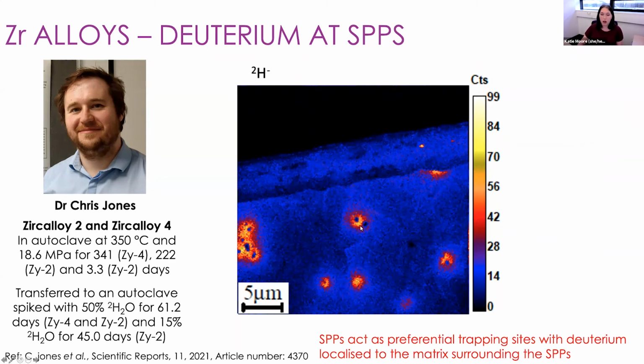So we also worked with some collaborators who did some DFT modeling just to be sure that the deuterium was localized in the metal matrix around the SPPs and not in the SPPs themselves. And that was confirmed by DFT. So this is what we're seeing. We're finding that these SPPs are acting as preferential trap sites for the deuterium in the matrix surrounding the SPPs.